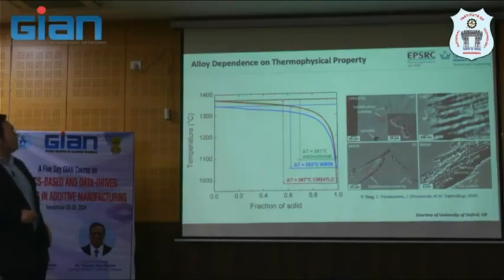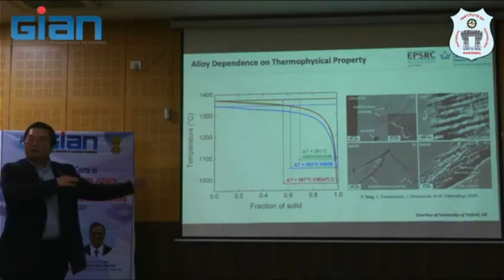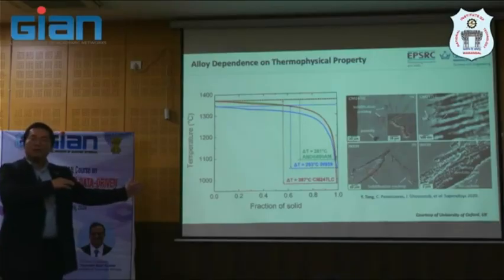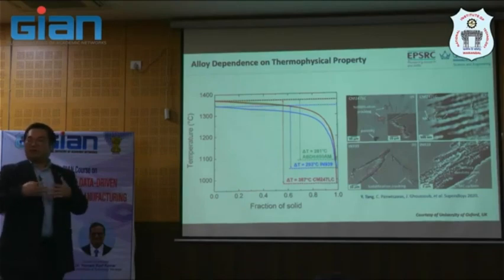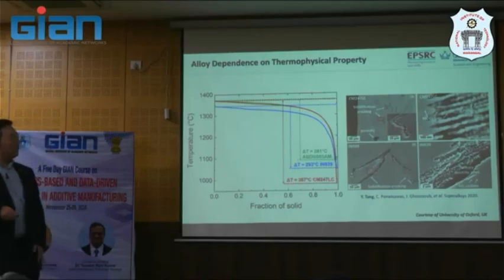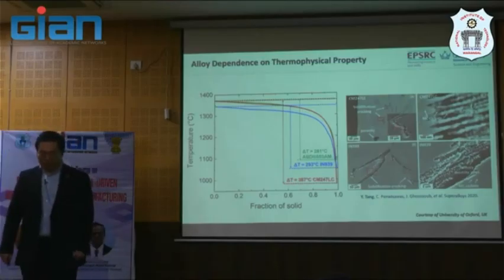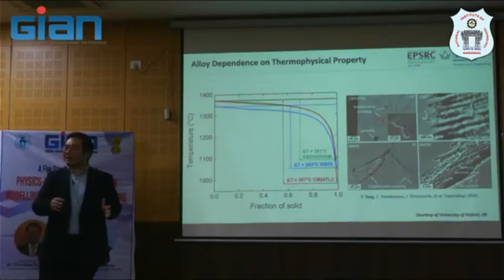And then it's not just that, because previous work from the quantification shows there will be some overlap or correlation of the defect. Again, there is not yet a high throughput experimental way that we can characterize or map this. Because nickel is probably more difficult than titanium. You know, the density of nickel is about twice that of titanium. And this may pose some challenge in terms of XCT, when you may have a smaller sample size than titanium, for example.